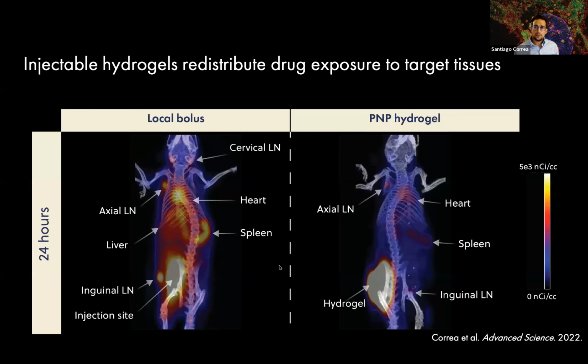Here are just two representative images of biodistribution of this antibody 24 hours after administration. On the left here, we see the local bolus, these warmer colors indicating higher concentrations of antibody. And what we can see is that at 24 hours, we're already seeing a lot of antibody getting to off-target tissues like the liver, the spleen, the heart, and distant lymph nodes. As opposed to our polymer nanoparticle hydrogel, or PNP hydrogel, where almost all of our drug is still retained in the hydrogel or the surrounding injection site.